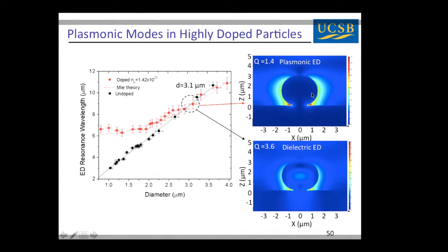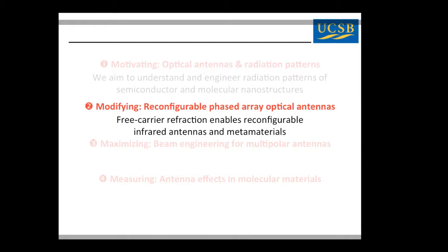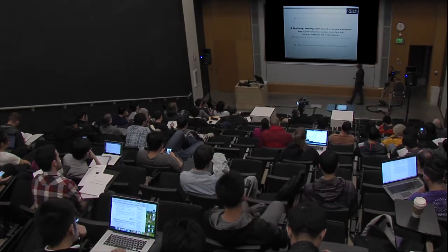The signature that identifies this as a plasmonic mode is that at very small sizes, the electric dipole resonance wavelength plateaus. This is a signature of what's called an electrostatic resonance, a size-independent or scale-independent resonance. Here we know that at this wavelength and this doping level, the dielectric function of silicon is around -2. To summarize this part of the talk, my group is pushing towards using these free carrier refraction effects in semiconductors to make reconfigurable infrared optics, things like optical antennas and metamaterials.